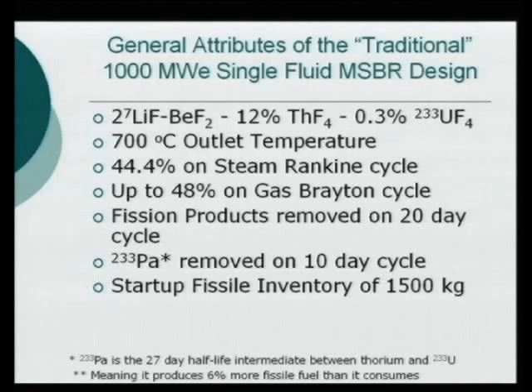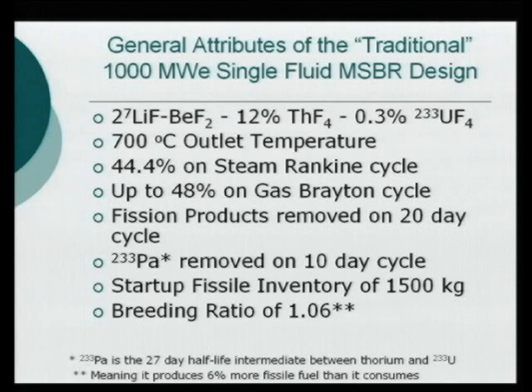It has a very low fissile inventory. We talked before about like 12 tons, 20 tons. This is only 1.5 tons, or 1,500 kilograms, for a typical gigawatt or 1,000 megawatt size plant. It has a breeding ratio of 1.06, which is modest compared to the fast breeder reactor, but you don't need to breed much fuel to start your next reactor. So that means the fuel you burn in a year, which is about 800 to 1,000 kilograms, you end up with 6% more than that at the end of the year.